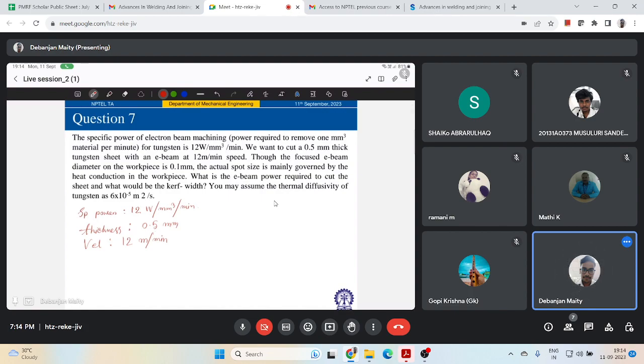And then it says, though the focused e-beam diameter on the workpiece is 0.1 mm, so dB is 0.1 mm. The actual spot size is mainly governed by the heat conduction in the workpiece. It's fine. So what is the e-beam power required to cut the sheet and what would be the kerf width? Basically the width of the welding region, the kerf. You may assume the thermal diffusivity of tungsten, which is given as alpha.